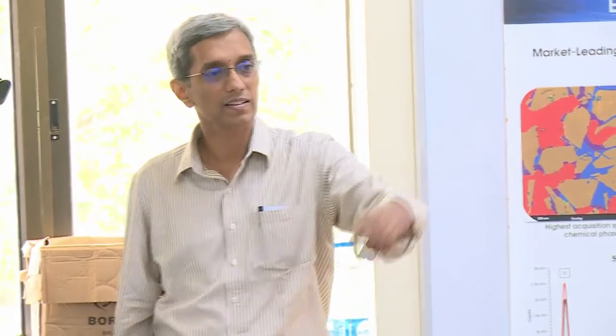I have one question. You showed that the DED patterns have much more detail than what you would get otherwise. Can we use those details to get elastic strains? That's the assumption. Yeah, we currently have a study going on with a university right now to test it. Because if I can do that, then I can calculate, at least in 2D, an average dislocation density. And I mentioned the central symmetry and pseudosymmetry problems. I think those patterns can help us with that too, because I don't think we can see that kind of detail in our regular CCD, and certainly not in the CMOS patterns.